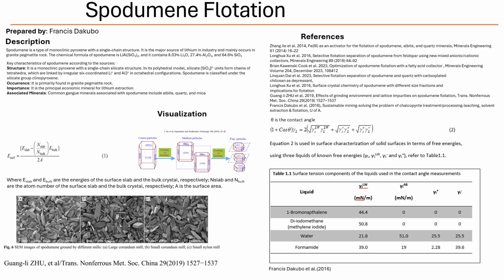Okay, so bringing this all together for optimizing the actual process, conditioning seems really important. That mixing stage before flotation. Crucial. Conditioning is where you mix the ground ore slurry with all the reagents: collector, depressant, pH modifiers, activators. How you do this matters a lot. What parameters? Things like the pH you adjust the slurry to, the dosage, how much collector you add, the conditioning time, how long you mix it, and even the mixing intensity, the power density.